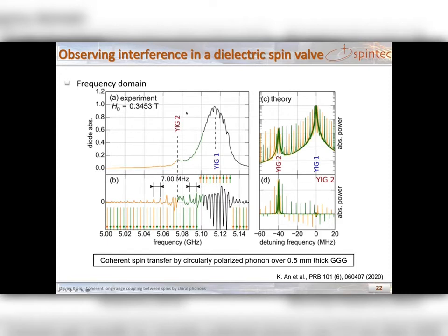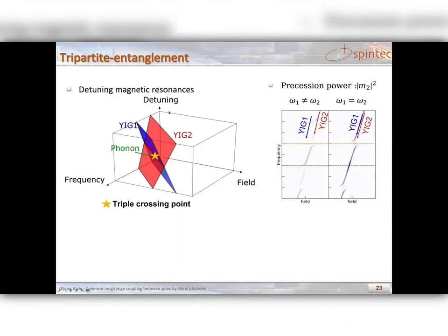So this indicates that YIG2 reflects the microwave power rather than absorbs. And through this observation of interference, we can clearly show that spin transfer occurs coherently via circularly polarized phonons over this very thick YIG-GGG substrate. So now, can we go further?